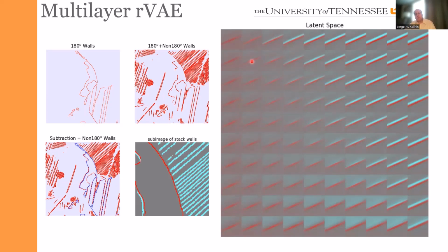So what that tells you is that if you fix the domain wall in the center, the positions of the edges close to the edges of the scan would be changing, which means that the wall undergoes this type of libration dynamics. And basically it tells me if there is no ferroelastic wall, the ferroelectric domain wall is very mobile. And the way you interpret the data here is essentially this is coming from these regions where the ferroelectric wall is pinned not by a single ferroelastic wall, but by the multiple ferroelastic walls perpendicular to it.